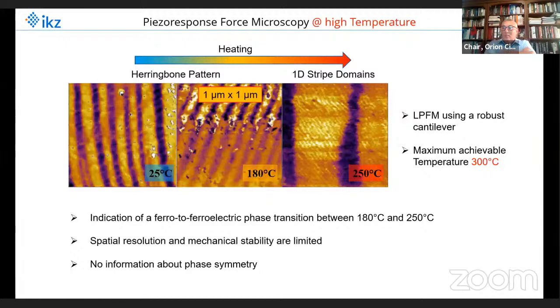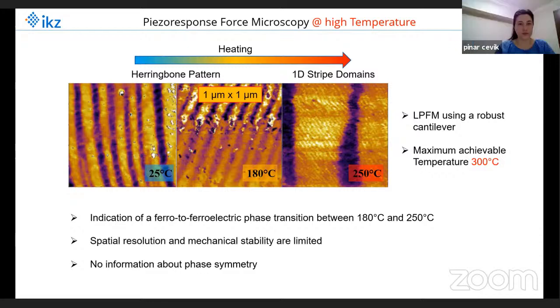So when we heat up to 180 degrees C, nothing has changed. Of course, we see some thermal drift, but when you further heat, let's say up to 250 degrees centigrade, you see an abrupt change of the domain pattern. So you see here a striped domain pattern. So we really observe here ferroelectric to ferroelectric phase transitions within the temperature range of between 180 degrees C and 250 degrees C. However, as you know, PFM does not give you any information about phase symmetry.